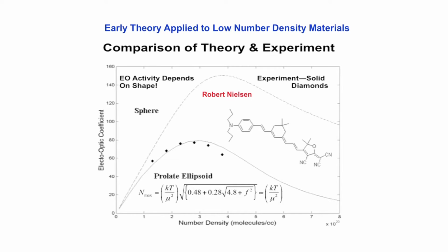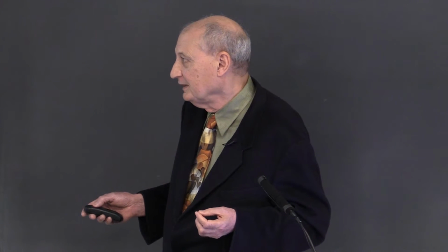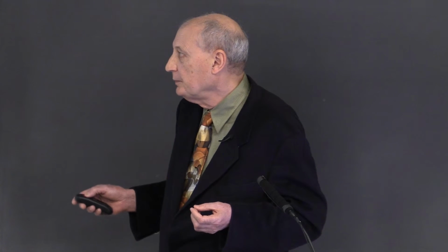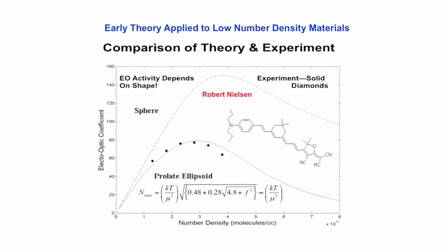So my grant monitors at the federal agencies asked me to explain this, and fortunately we have Bruce and his students as well as myself involved. And so what we're able to do is model this by treating this chromophore as a single ellipsoid, so it's a coarse-grained approximation to the chromophore, and we're going to take into account the fact that this has a significant dipole moment. So the reason that this curve rolls over is dipole-dipole interactions between chromophores tend to drive centrosymmetric organization.